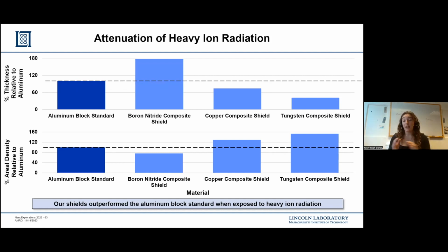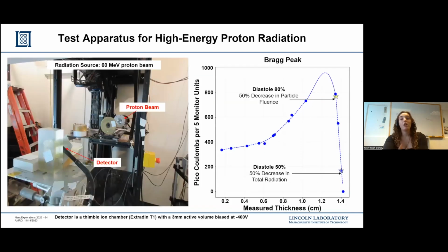However, because heavy ion radiation is dominated by inelastic scattering, when we change our metric to areal density, the boron nitride shield outperforms the aluminum block standard. Either way, we are able to outperform the aluminum block standard. Finally, we did proton radiation.